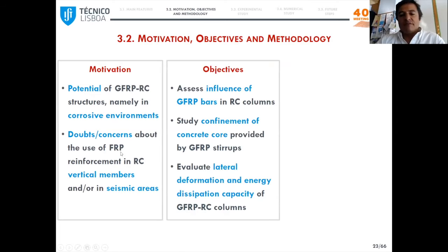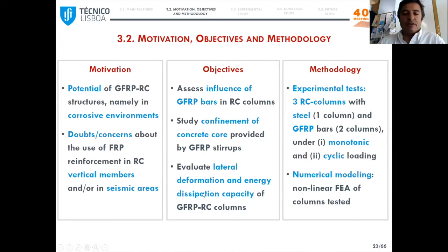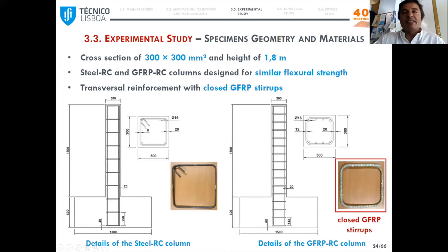So basically the objectives were to assess the influence of GFRP bars in concrete columns, to evaluate the lateral deformation and energy dissipation capacity of concrete columns, and also to study the confinement of the concrete core provided by these closed GFRP stirrups. So to this end, so far we did 3 full-scale tests in columns, 1 with steel rebars as a reference, and 2 with GFRP bars under monotonic and cyclic loading, and also the numerical simulation of these tests.